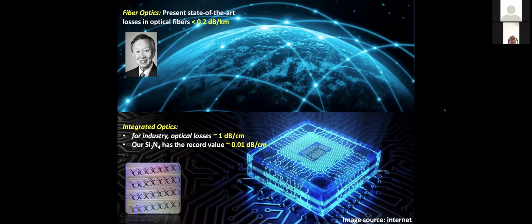Central to photonics is the waveguide loss. So far, the lowest waveguide loss has been achieved only in fiber, which is 0.2 dB per kilometer, and which makes global fiber communication possible, thanks to Charles Kao. In integrated photonics, for industrial applications, the optical loss is typically on the order of 1 dB per centimeter, whereas our integrated photonics based on silicon nitride has a record value of 0.01 dB per centimeter, 2 orders of magnitude lower than this value.